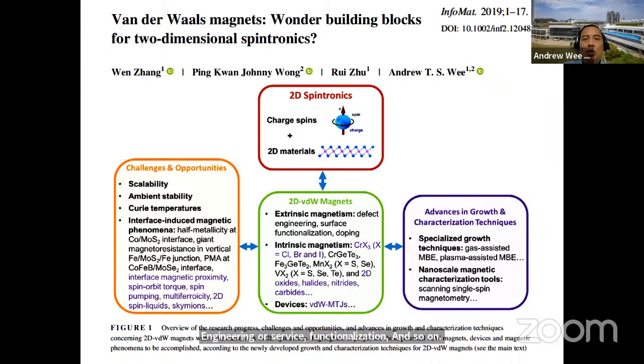And of course, in order to commercialize this field, we must be able to grow these materials using specialized growth techniques. We must be able to grow them in a scalable way. We must be able to grow them such that they have ambient stability and high Curie temperatures. Curie temperature is a temperature below which the material becomes magnetic. So the Curie temperature has to be above room temperature. And we need to understand the interface-induced magnetic phenomena. Since these are 2D materials, the interface is very important. So we need to understand interface magnetic proximity, spin orbit torque, spin pumping, multiferroicity, and so on. So there's still a lot of work that needs to be done.